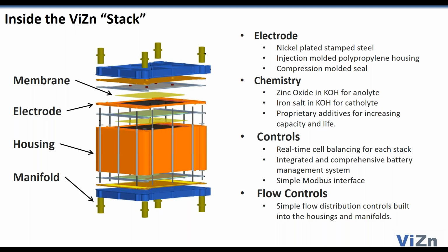Here's a little more detail on the stack. This is an exploded view of the ViZn stack. What you're seeing there is we really have electrodes with 30 cells. Each electrode is just nickel-plated stamped steel mounted in an injection molded polypropylene housing with some compression molded seals around it. Those are stacked up to make the battery stack.